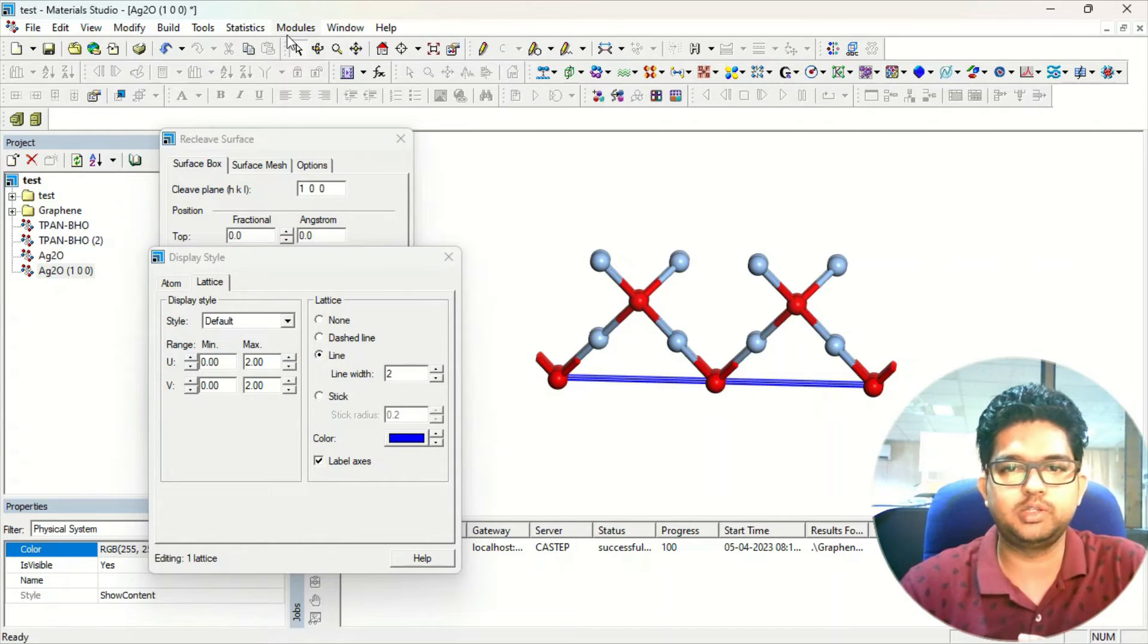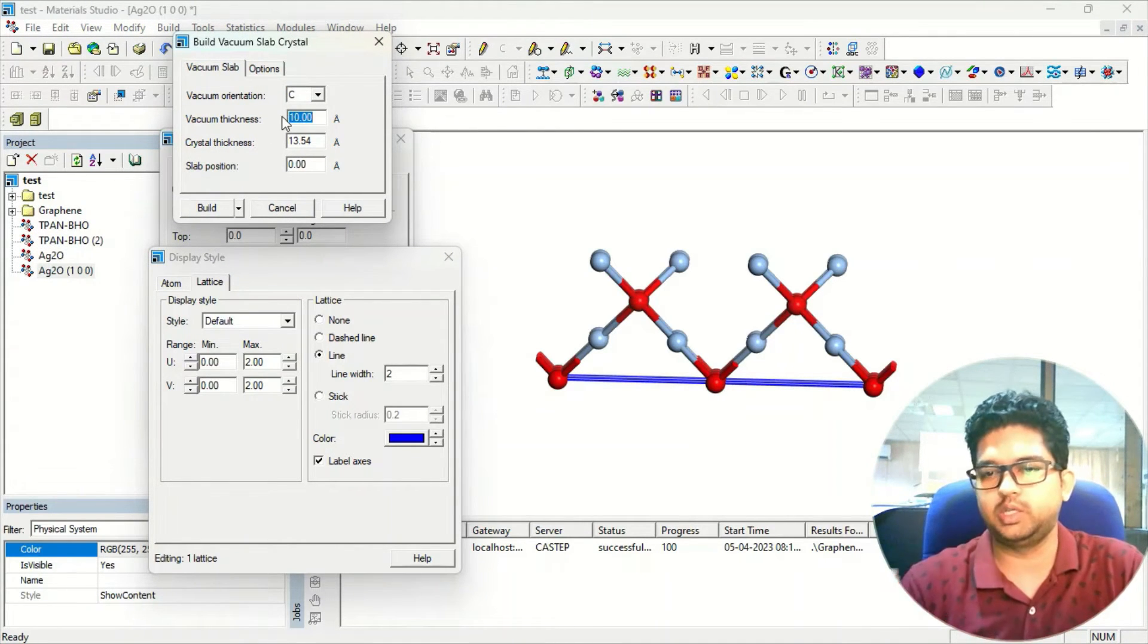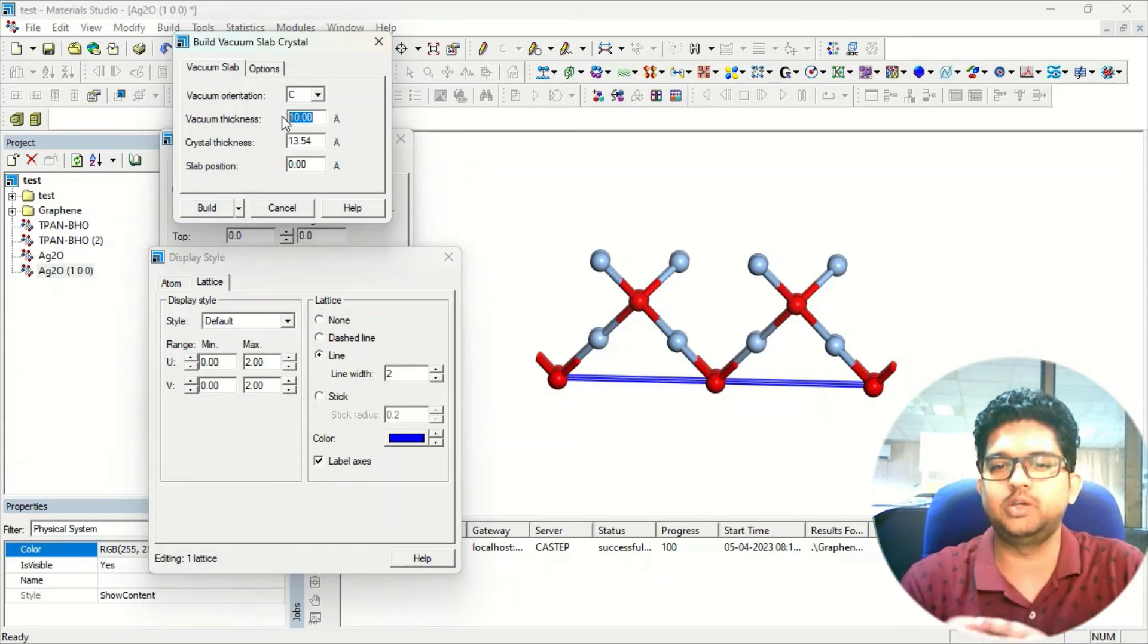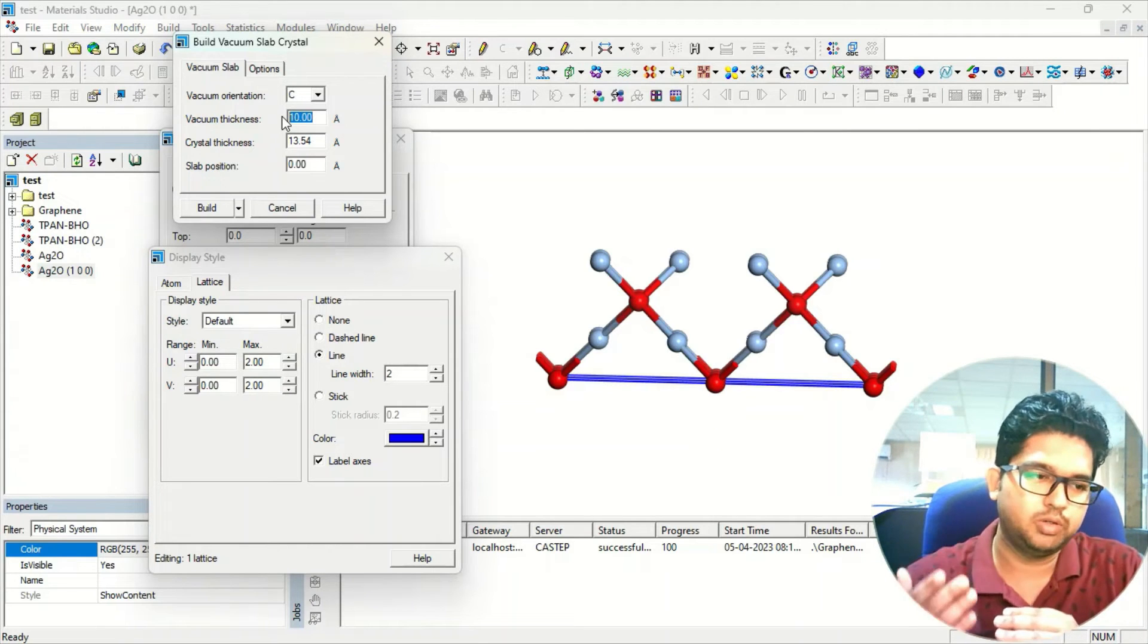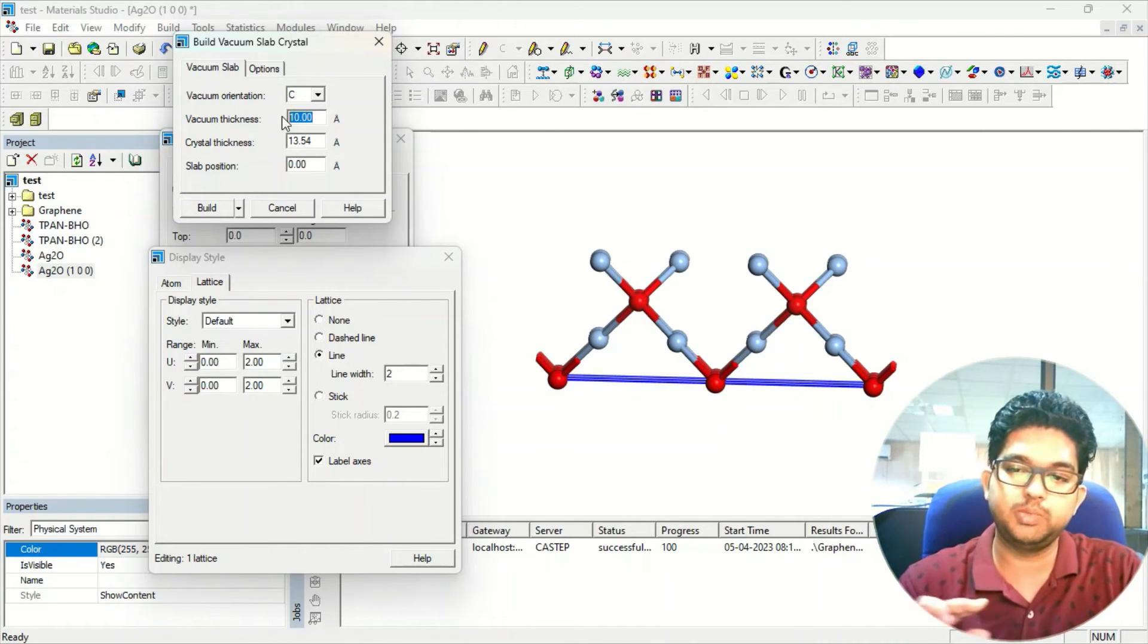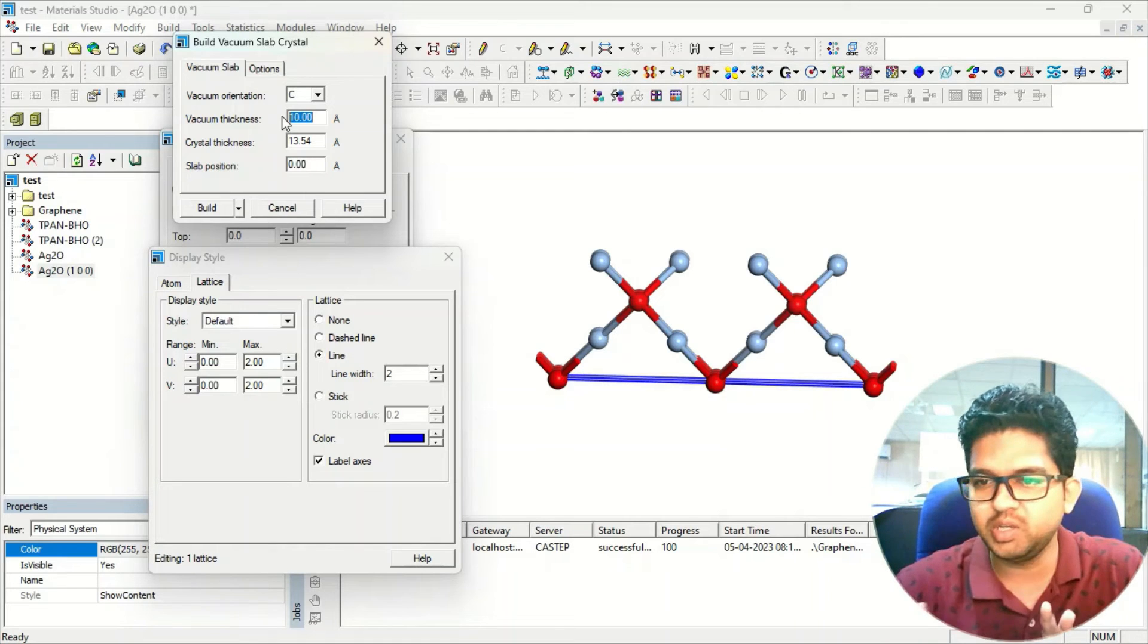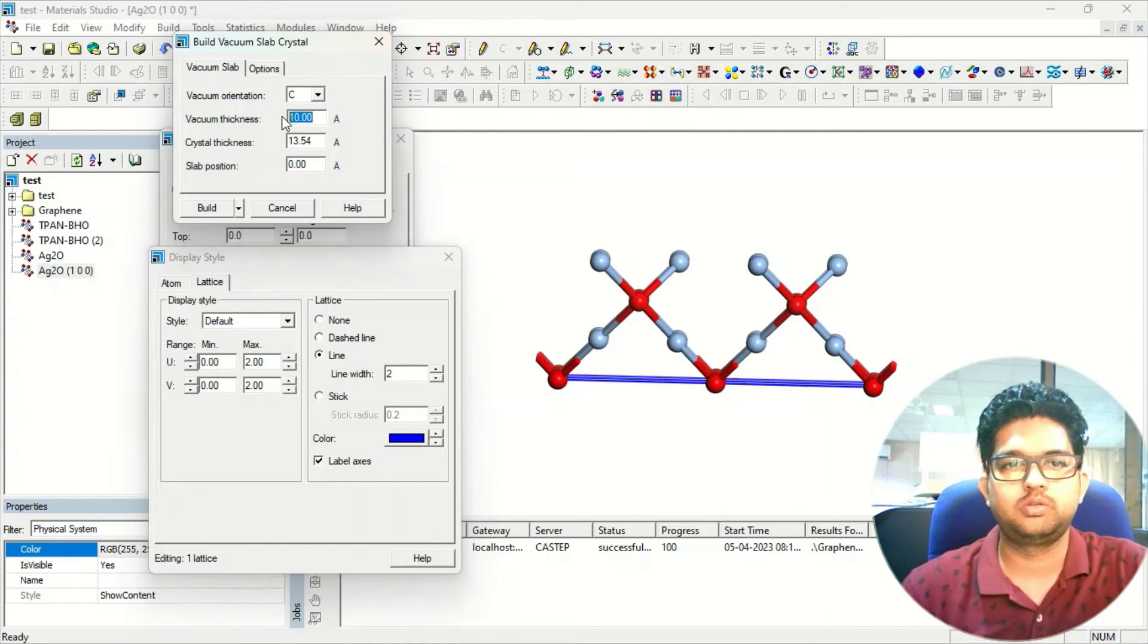Now the Z axis, the C axis is perpendicular to this. So what we will do is, this is the vacuum thickness. What thickness you want to give? Generally, we give thickness more than 10 angstrom so that interaction between those layers will be minimal. Generally to avoid these, like if you want to have interaction between those layers, then obviously you have to give lesser thickness. If you want to study just the two dimensional nano-sheet, then the thickness has to be more than 10 angstrom, at least in between 10 to 15, so that there is no interaction. Generally, 10 is also fine. There will be no interaction, like no covalent interaction or no weak interaction in that range.